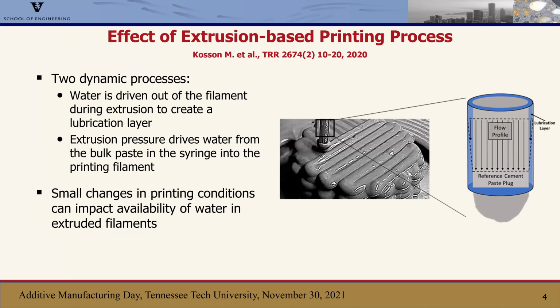There are a couple considerations that are important to take into account when you're extruding a cementitious material, particularly with the propensity for it to segregate during the extrusion pressure. So there's a couple dynamic processes that occur during this process. Water can be driven out of the extruded filament into a lubrication layer to facilitate plug flow, which can change the availability of water within the filament, while simultaneously you can be driving water from the bulk cement paste into the filament as it's printing, which can have a converse increase of the local water availability within an extruded filament.